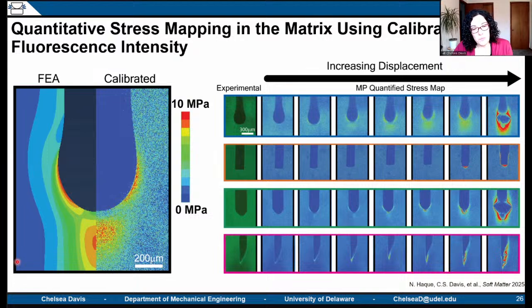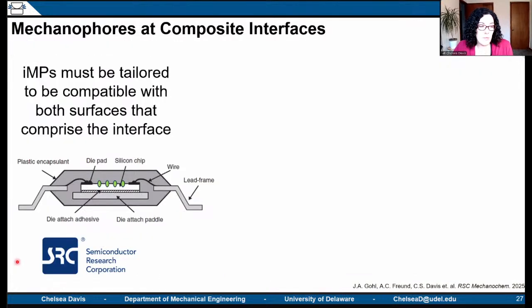But my background has always been caring more about interfaces than bulk deformation. So I was always curious and have been wanting for a very long time to install mechanophores at the interface between a reinforcing particle and the polymer matrix, rather than putting the mechanophore in the bulk itself. And I had this opportunity when my group was awarded a small contract from the Semiconductor Research Corporation, where in microelectronic chips, there's a concern when you have microelectronics that are sensitive to humidity and oxidation and all sorts of environmental degradation modes that are always encapsulated in some form of polymer matrix.